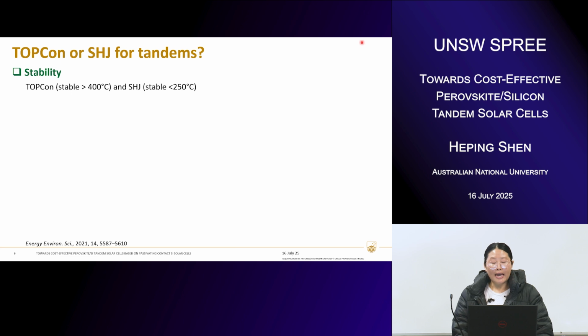Okay, and moving to the next important aspect, we are looking at the golden triangle of the solar cell, right? So the stability. Here I would like to mention an important stability aspect, which is the thermal stability. TOPCon shows clearly better thermal stability compared to silicon heterojunction. TOPCon can be stable up to 400 degrees and above, but silicon heterojunction will degrade when the temperature is above 250. So this feature is very important.